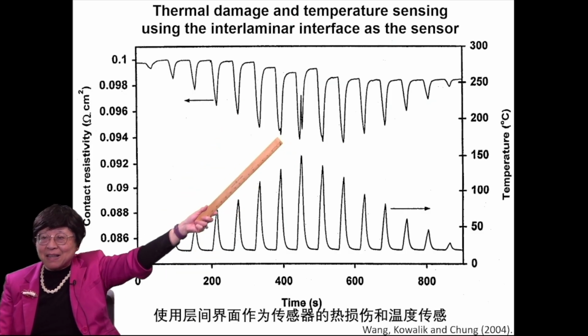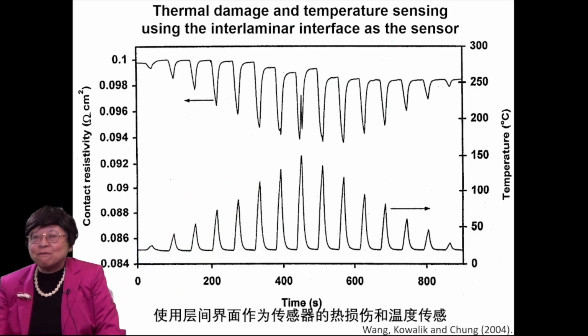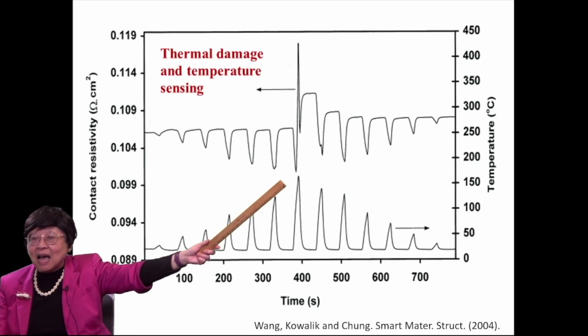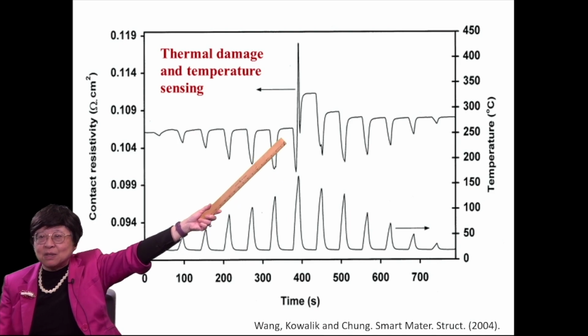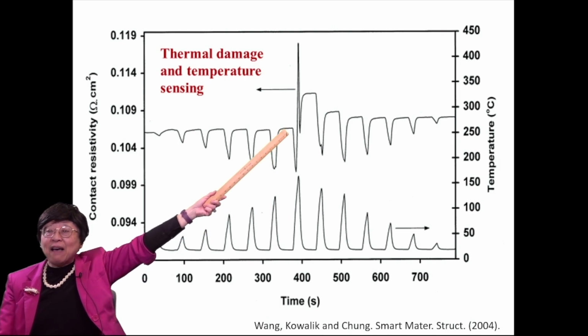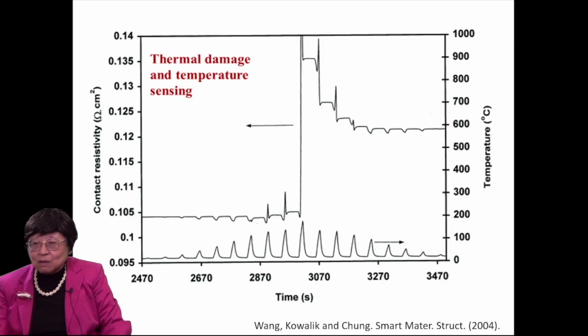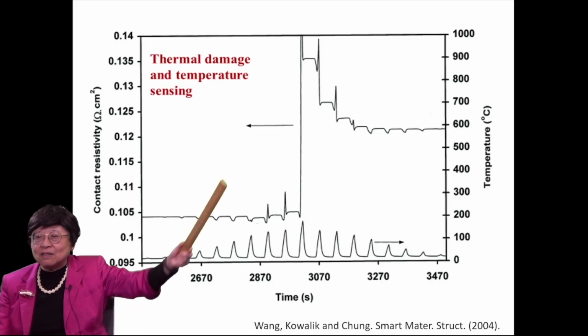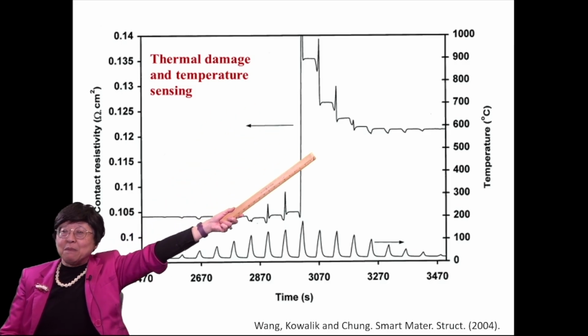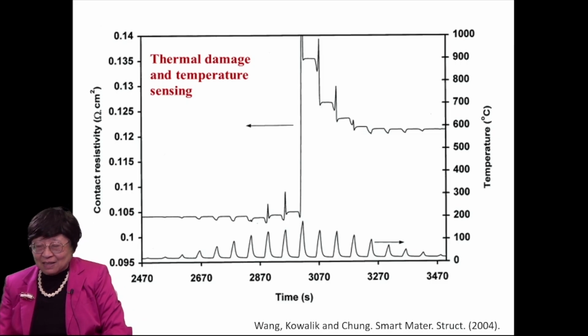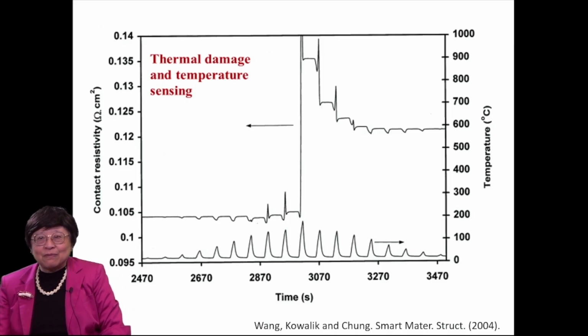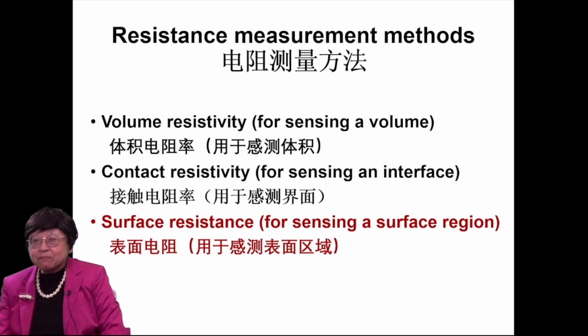shoots up like that. That's an indication of some very minor thermal damage. If we raise the highest temperature, then that shooting up becomes more prominent, and you have some aftermath there. Still higher temperature, then the shooting up becomes even more, and the aftermath becomes even more prominent. So the interlaminar interface is a very sensitive sensor for temperature as well as thermal damage.